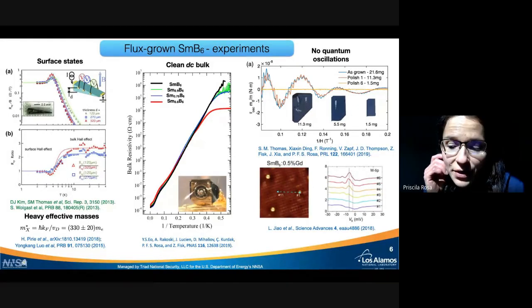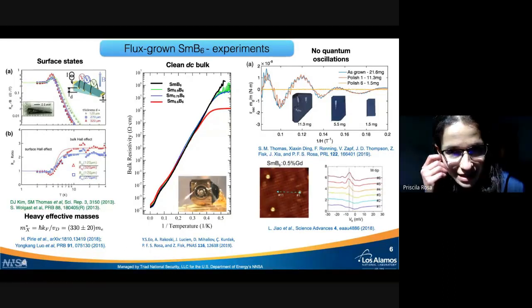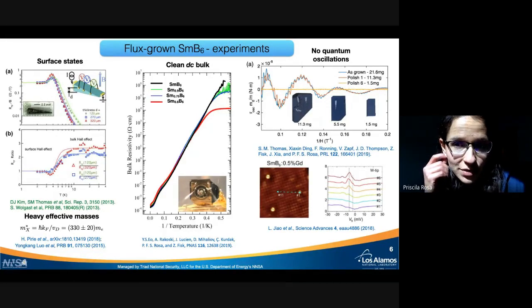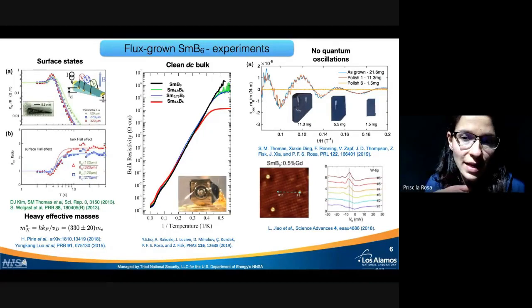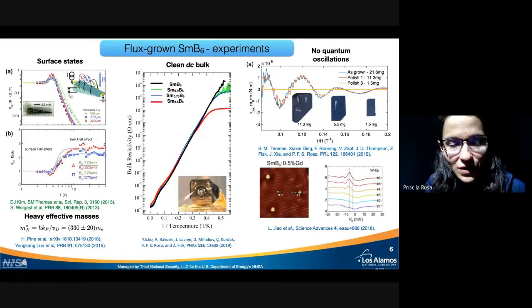But the story is actually more complicated than this, and it's still going on. I can tell you really quickly. There are two types of samples. This is the sample I synthesized. They are grown by flux, by aluminum. However, there's a second way of growing these crystals, the so-called floating zone method. And in those samples, they also see quantum oscillations. In that case, it cannot be coming from aluminum because they are not using aluminum flux. So there is still the question: if there are no quantum oscillations in these samples, how come they exist in the other samples? And that's a question that is still open.